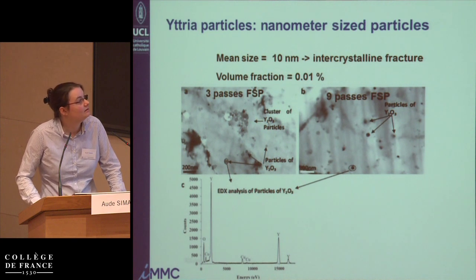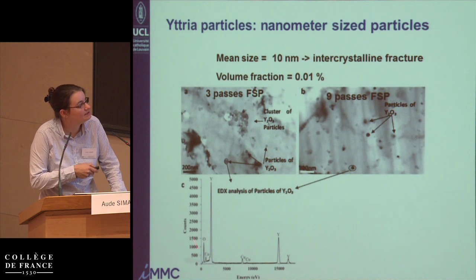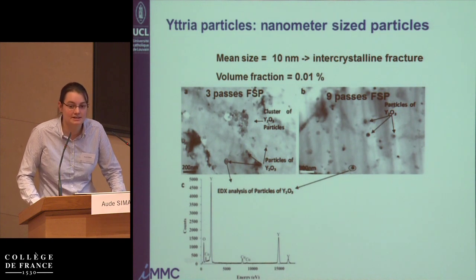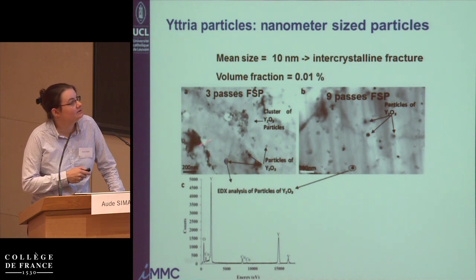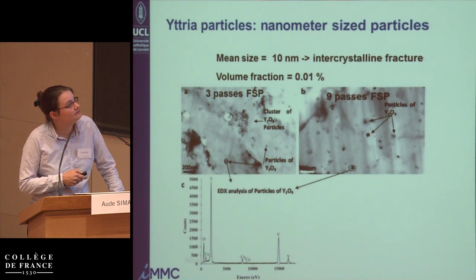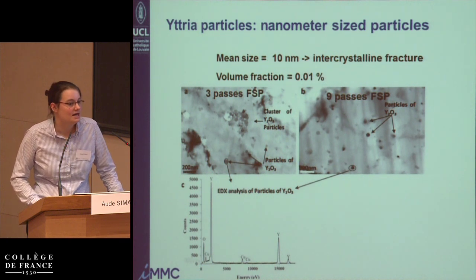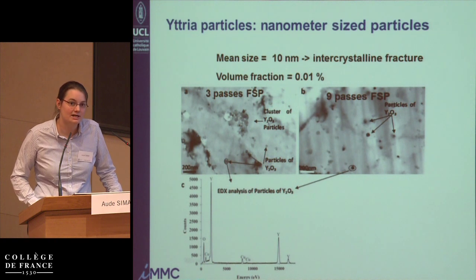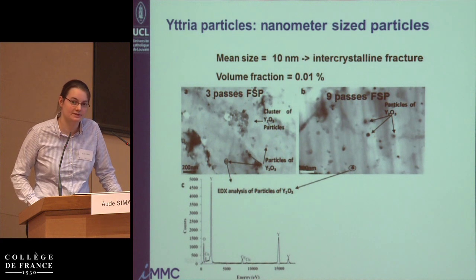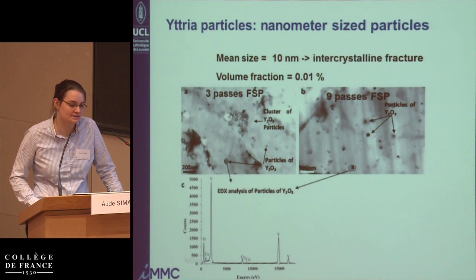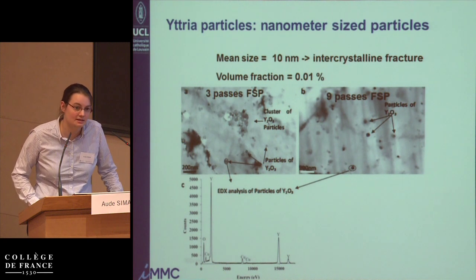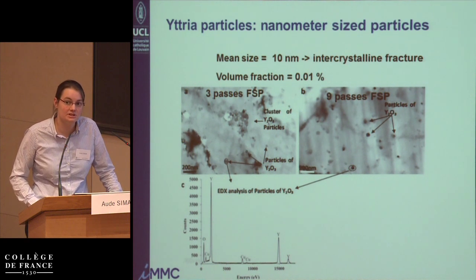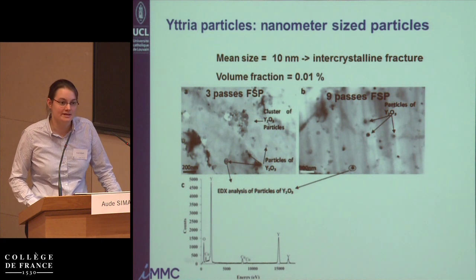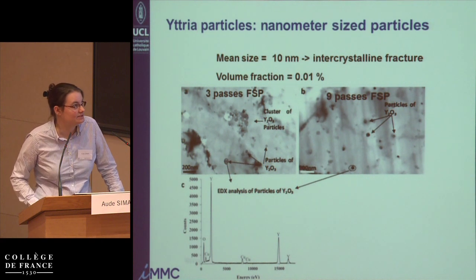you see yttrium particles that have been identified by EDX in the transmission electron microscope, and you see that these particles are about 10 nanometers in size, and so that was the crystallite size. So we actually broke the particle and got some pieces of the crystallites that compose this particle. That's very interesting to see that we can actually reach such sizes. And so we can make nanocomposites with this processing method.